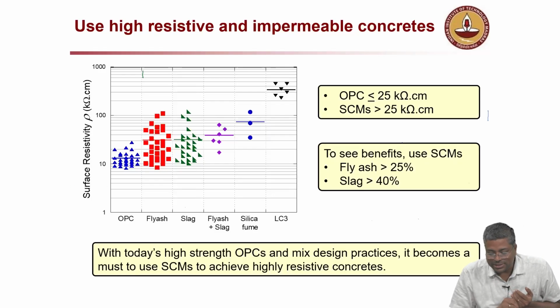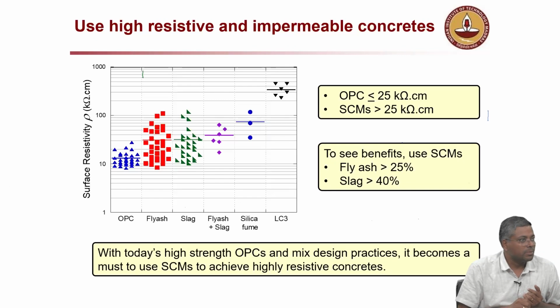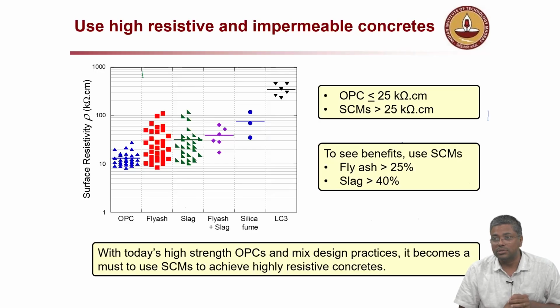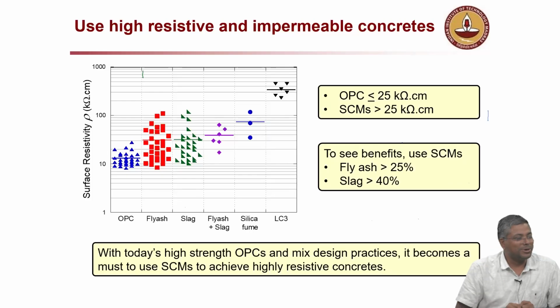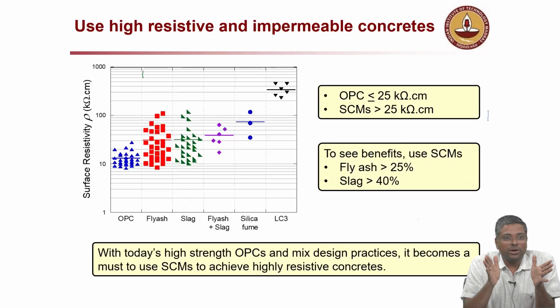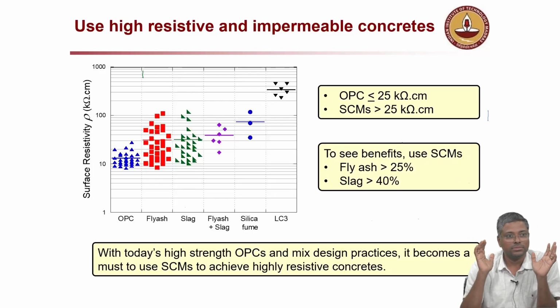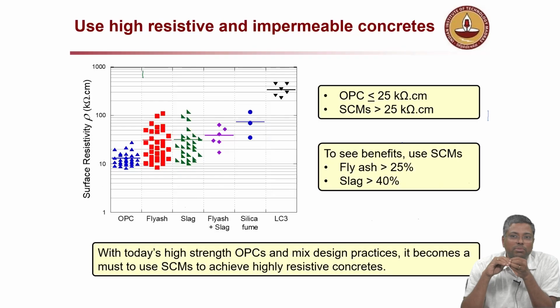Okay, now you can see that on the right side, I think that we did not discuss at that time. Okay, so that minimum quantity of fly ash, so that you actually see the benefit of fly ash, is at least 25%. If you do not put that much, it will not really show. I was thinking that the sign is reverse or not. Okay, so minimum 25%. If it is slag, minimum 40%. If you don't see this much, let's say if somebody is coming up with a mix with 10% fly ash, please don't call it fly ash concrete. It's not. Okay, it's too little a quantity to see the benefit of fly ash.